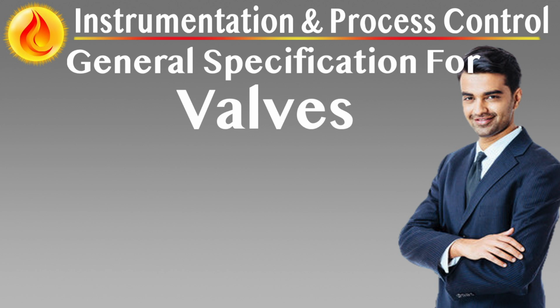Seat and trim materials must be carefully selected based on service fluids and operating temperatures. Electroless nickel plating, ENP, is not permitted on wetted parts such as balls or seats. Instead, preferred materials include tungsten carbide, stellite, or other approved coatings with high wear and corrosion resistance. For ball valves, solid one-piece cast or forged balls are mandatory. Welded or fabricated balls are prohibited due to potential failure under cyclic or thermal stress.